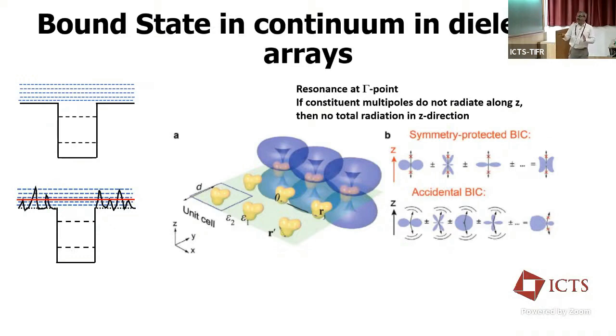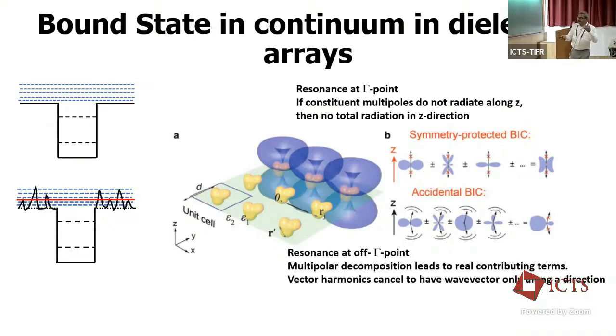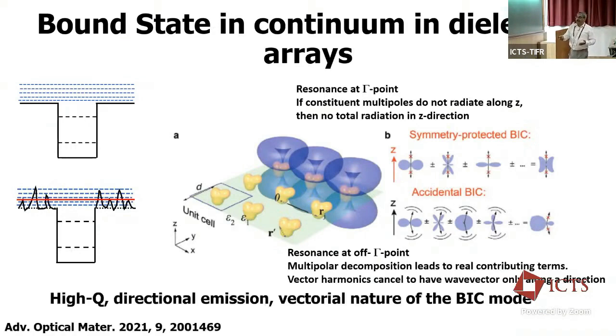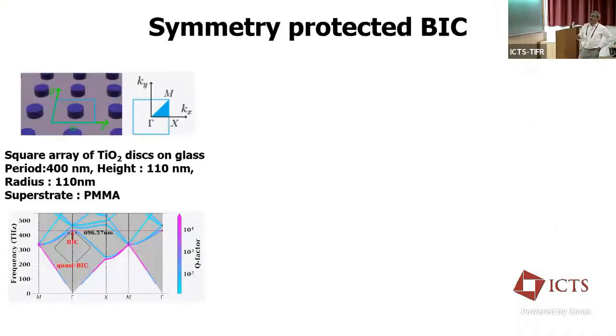So what this means is that if you have a dipole emitter inside this medium, you can have directional emission. And in addition, mathematically, these are high Q, or in fact infinite Q factors. Zero line width mode is mathematically what you get for these BIC resonances. So you can make use of it to have strong light matter interaction to get large emission and also directional emission from these BIC resonances. Another interesting thing is this is of vectorial nature. I'll show some examples of this.